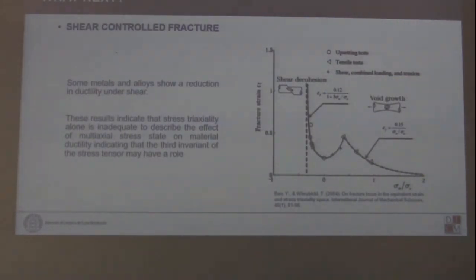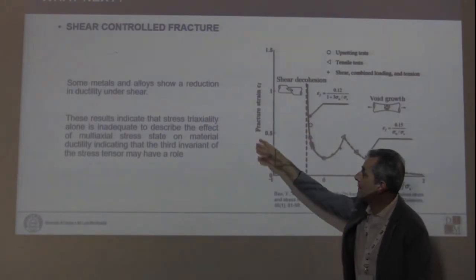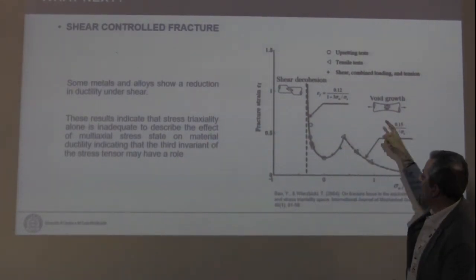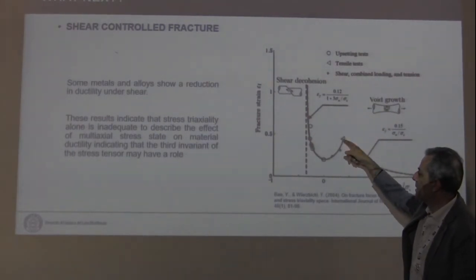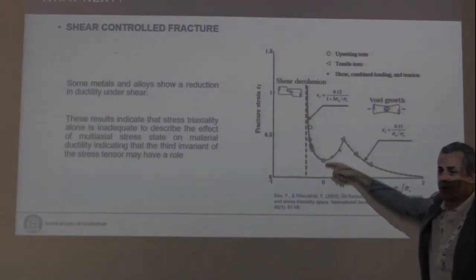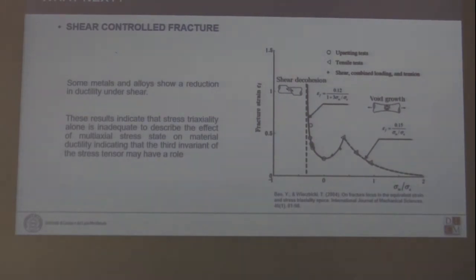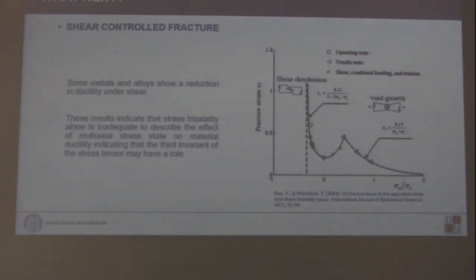What next? Where is the research going right now? The research in continuum damage mechanics is now moving to shear controlled fracture. There was a lot of attention in the last 10 years on the possible role of shear, described by the Lode angle parameter. Everything relies on this plot provided by Bao and Wierzbicki, in which there is a cusp in fracture strain versus stress triaxiality, because the uniaxial strain to failure is here, this is torsion, and this is the negative stress triaxiality range. There is a lot of effort in trying to predict the material behavior there. There you need a different kind of model formulation. For instance, the formulation I just recalled doesn't account for J3, which is the third invariant of the deviatoric stress.